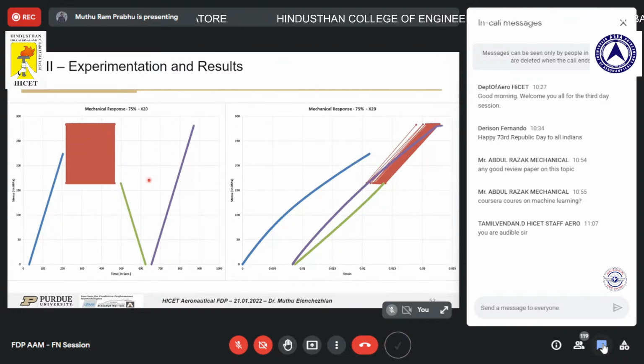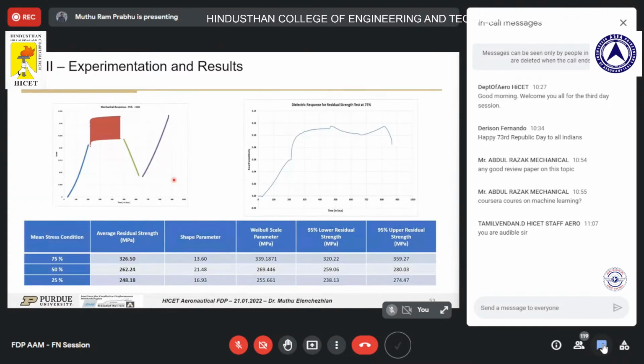And this was the mechanical response which was applied based on strain. So these are the strain values. And this strain value is again compared to the dielectric response over here. So this is the data that we got from the dielectric. This is during ramp up. This is during the fatigue curve. This is during the unloading curve. And this is during the second ramp up and during failure. And different residual strength values were obtained for the 3 different loading conditions.